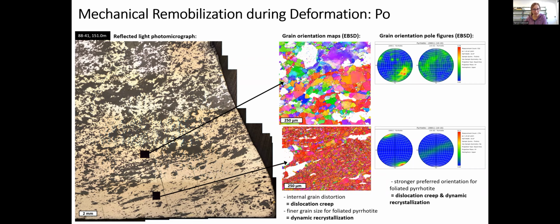Then if you look closely at some of the grains in both maps, if you zoom your eyes in over there, you can see that within the grain, there are variations in the color or the intensity of the color. So that shows that the crystallographic orientation is varying. So you've got internal distortion, so internal strain, which shows that you've got some deformation actually affecting these grains.